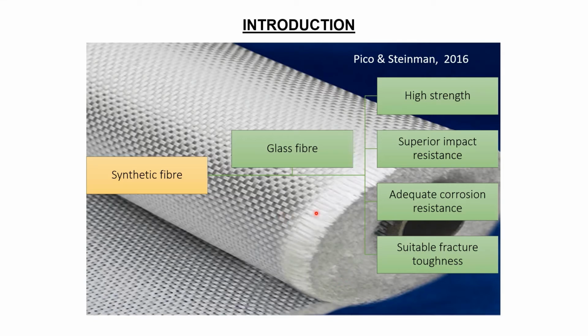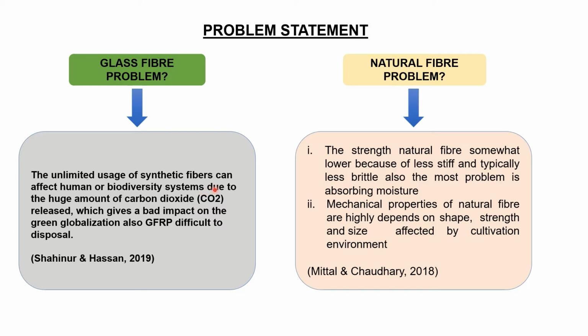Meanwhile, glass fiber has high strength, superior impact resistance, adequate corrosion resistance, and suitable fracture toughness. Both have their own problems. With unlimited usage, glass fiber can affect humans or the biodiversity system, and glass fiber reinforced polymer is also difficult to dispose of. Meanwhile, the natural fiber problem is that its strength is lower because it is less stiff and typically less brittle. Also, the major problem is absorbing moisture. The mechanical properties of natural fiber highly depend on shape, strength, and size, affected by the cultivation environment.